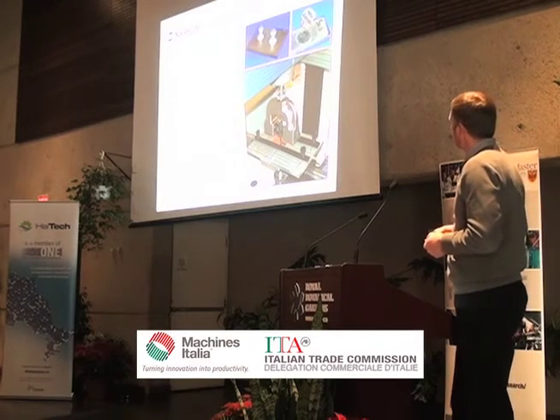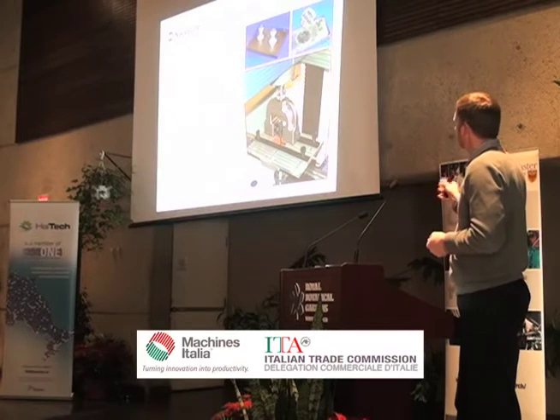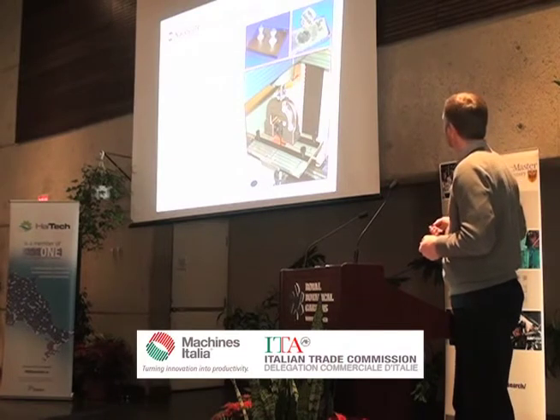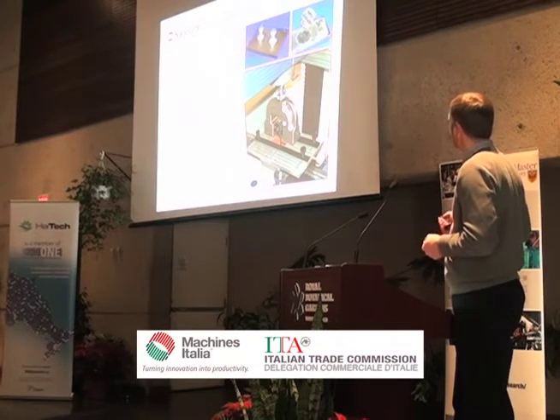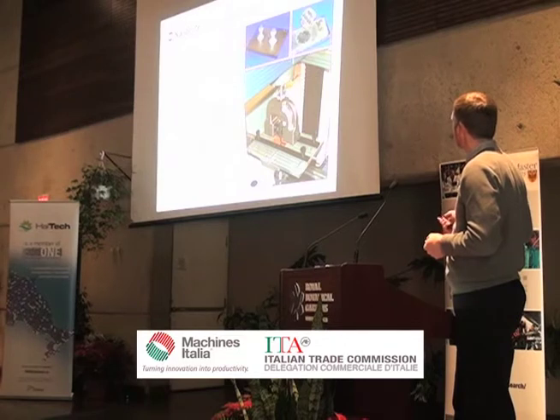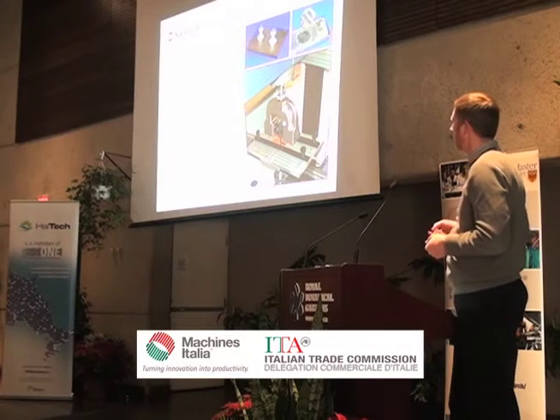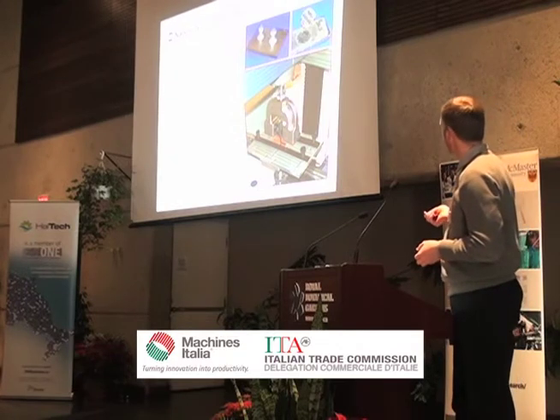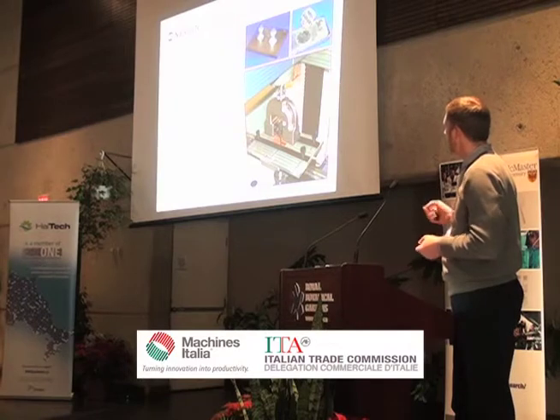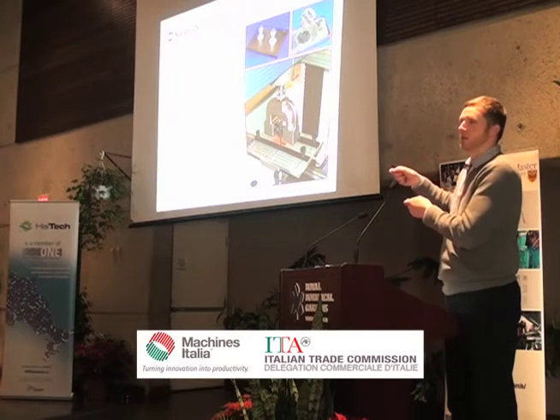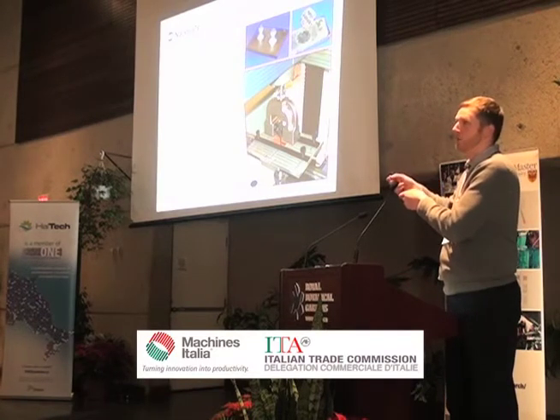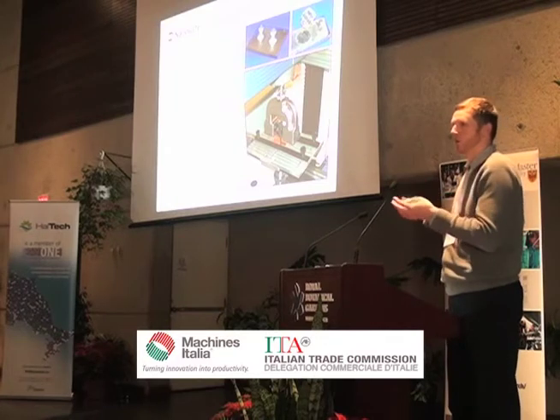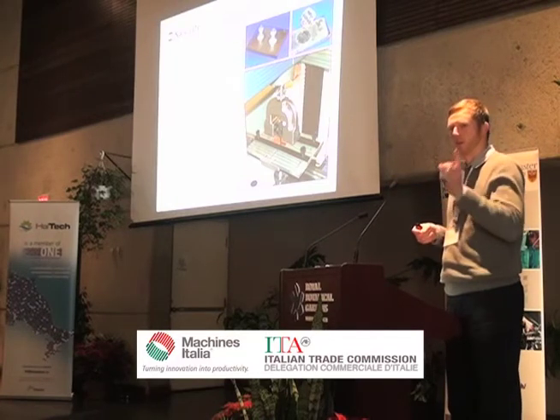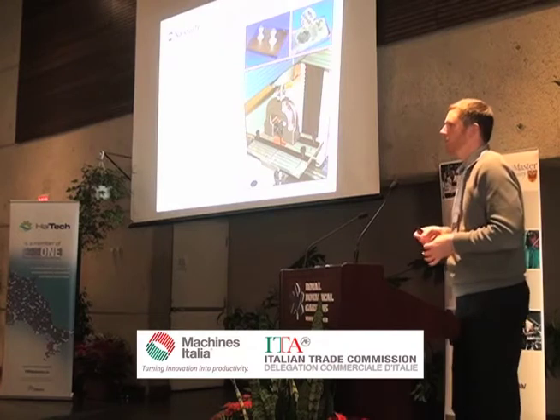This is more or less a pictorial example of what kind of tests we do to show the adhesion. This is a pull-off test, but more or less nowadays we use the peel strength test. So this is an example of a small coupon that's been treated with our in-bond material and then metallized, and we peel the top level away from the composite substrate, showing that you get a good degree of adhesion. I've got one example in my bag here, which I can show you afterwards.